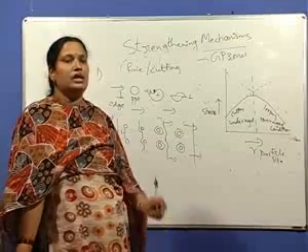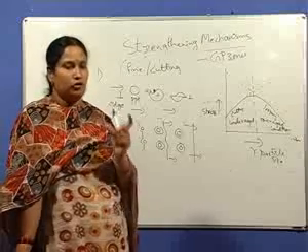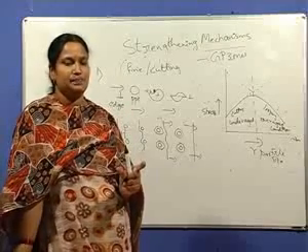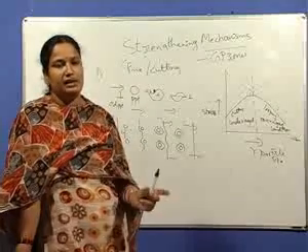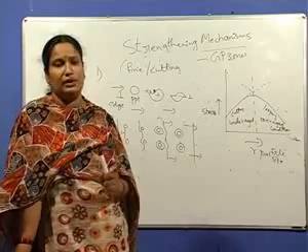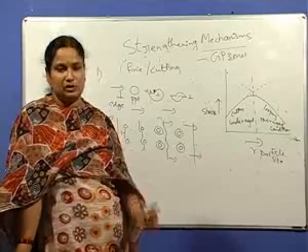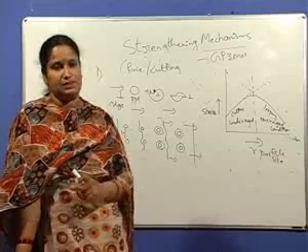And moreover, in any precipitation hardening system, the main phases are the formation of a coherent precipitate phase, where the peak hardness is achieved, and then a coarse precipitate which is not coherent with the matrix phase forms at higher or longer aging times.